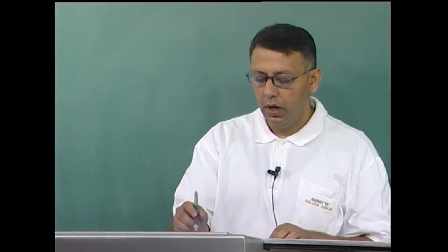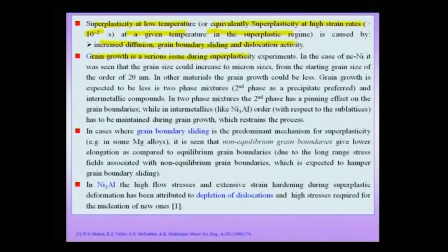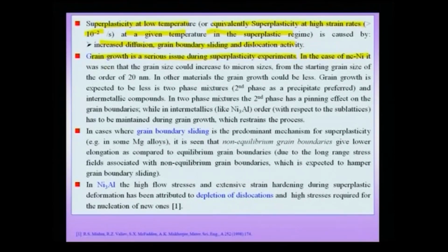Like in the case of creep, grain growth seems a very serious issue during superplasticity experiments, and if grain growth is going to take place and your expected superplasticity mechanism is grain boundary sliding, then obviously the elongation you are going to get is going to be limited purely because of grain growth issues. In the case of nanocrystalline nickel, it was seen that the grain size could increase to micron sizes starting from a grain size of the order of 20 nanometer. So, this is happening during the testing, that means during superplastic forming the grain size is increasing from about 20 nanometer to something of micron size, which is a very serious issue in superplastic testing.